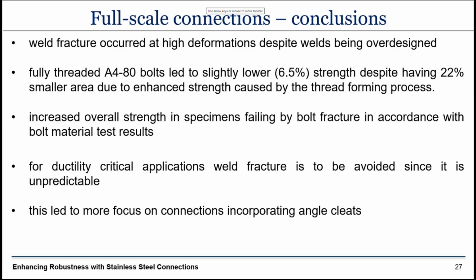So what we recommended was to avoid this sort of end plate connections for a number of reasons. One is that weld fracture is not very predictable at extreme events. It may be fine for normal applications where the design resistance depends on the plastic resistance of the joint. But in that case, we're talking about extremely high deformations.